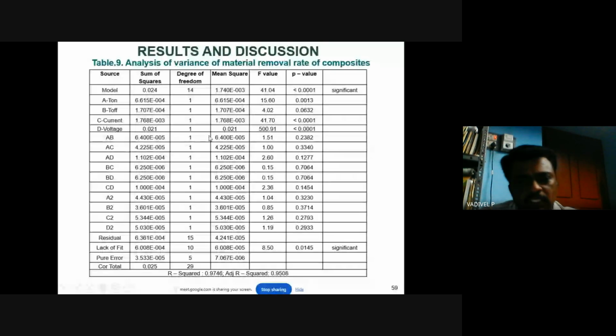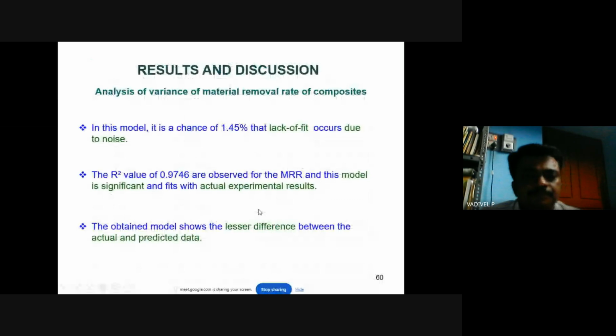So this is the ANOVA table. The ANOVA table gives the result as significant, showing the model sum of squares, degrees of freedom, mean square, F value, and P value. The R squared value we obtained is 0.9746, and the adjusted R squared value is 0.9508. So this is the optimum result we have obtained. In the analysis of variance of material removal rate of composites, the chance of a lack of fit of 1.45 percent occurs due to noise. The R squared value observed for the MRR is 0.9746, and this model is significant and fits the actual experiment results. The model shows a small difference between the actual and the predicted data.